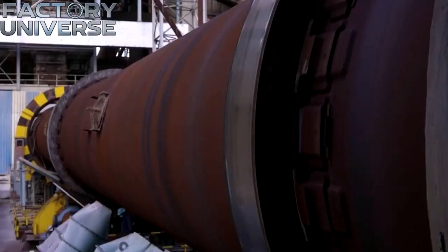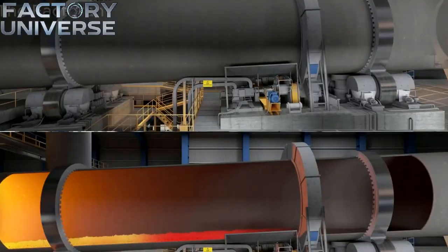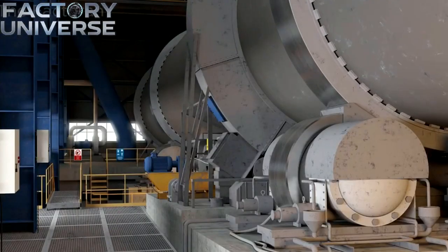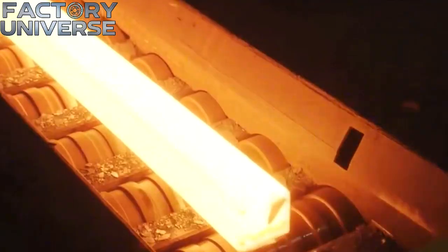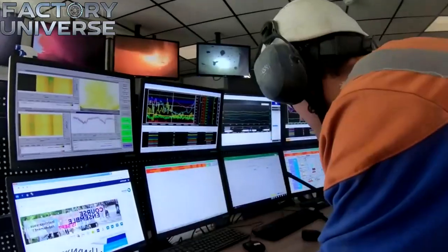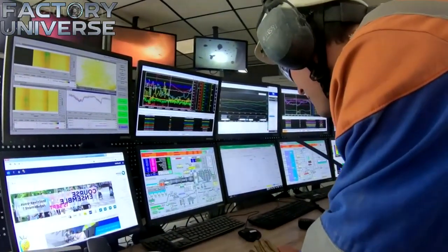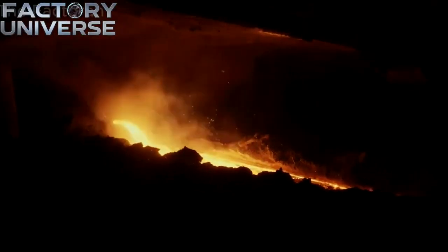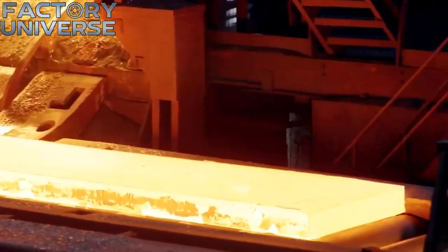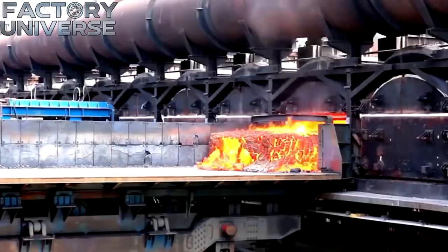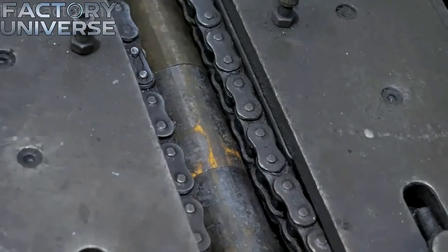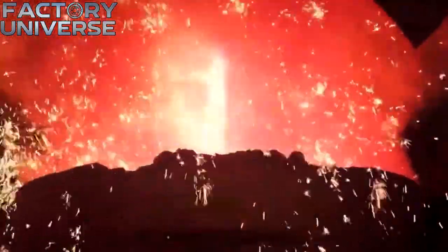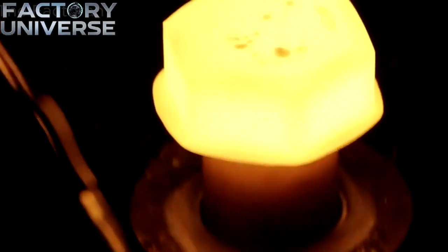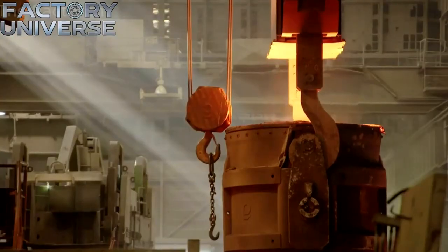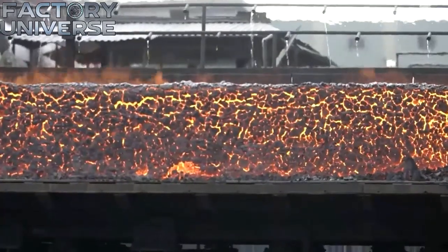One can notice how the molten iron, still radiating a blinding red heat, is transferred directly into the basic oxygen furnace. This colossal steel vessel is lined with thick refractory bricks to withstand the internal violence of the purification process. From above, a massive lance descends into the vessel, blasting a jet of pure oxygen at tremendous speed onto the liquid surface. The oxygen ignites instantly, stripping away carbon and remaining impurities in a chaotic display of energy.